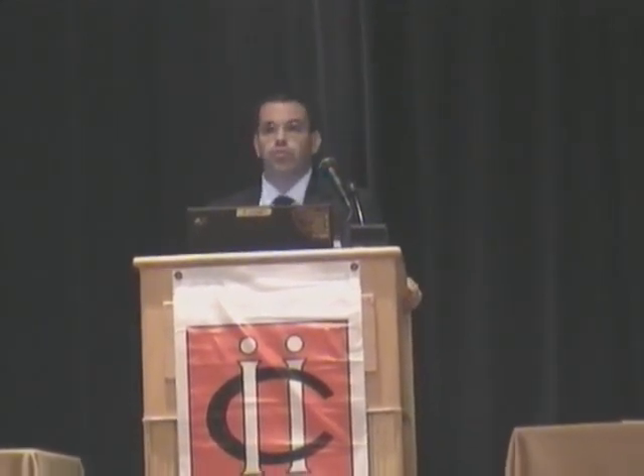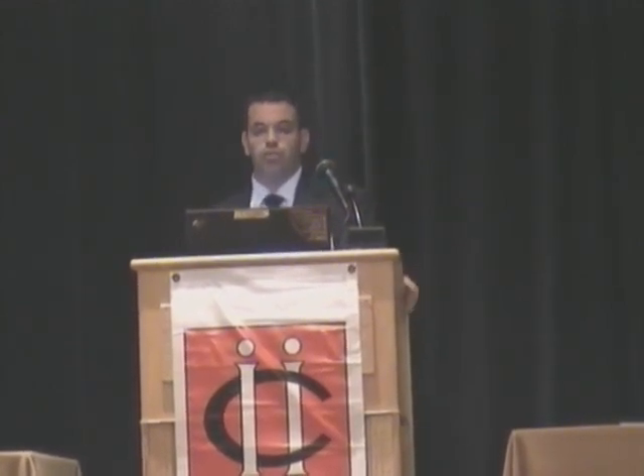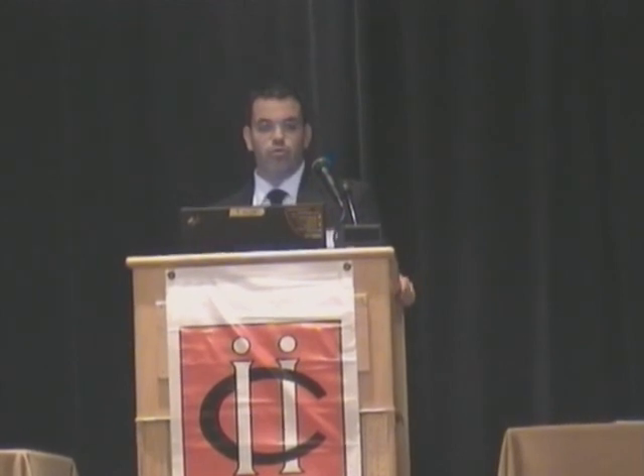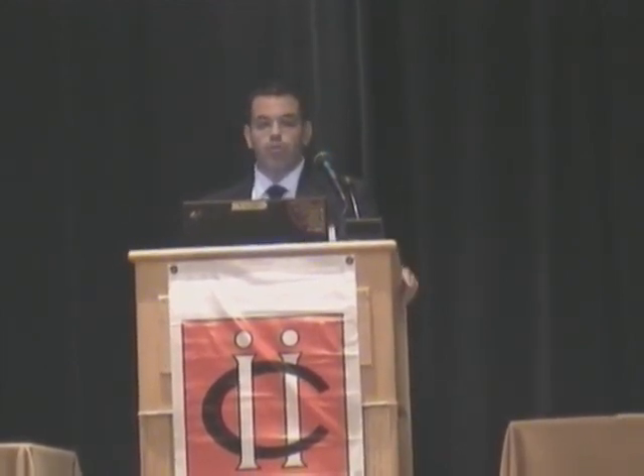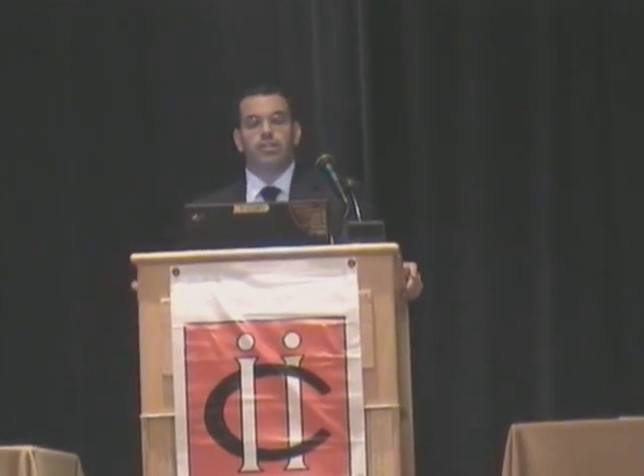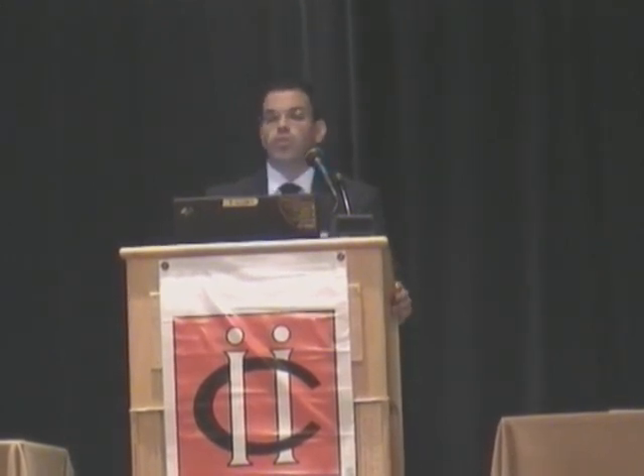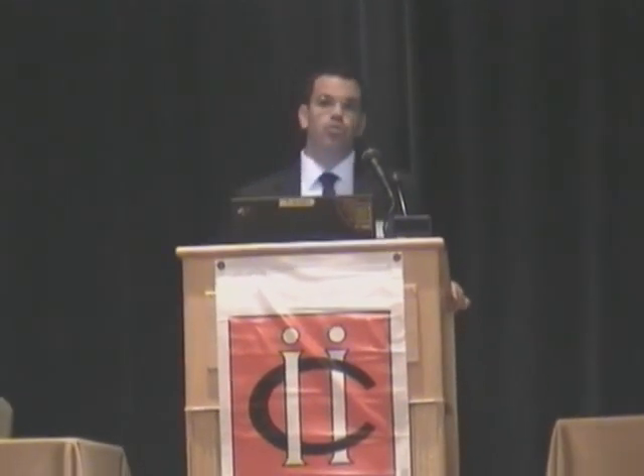So now we employ a new design method based on lessons learned from the first one. We plug the gates in the wax injection tool only after the FAI is approved. Then we remove all the chills. Design the wax assembly to be more industrialized, meaning that we were standardizing our runners and our gates, top and bottom frames, feed cups and filters, so everything will be the same. It doesn't matter what the size of the part, we're going to make a top and bottom. And most important, we're going to put as few gates as we can on the first setup, even if it means that it will go scrap. We don't care. We want to see how the aluminum flows, how it solidifies, what the actual problems are.